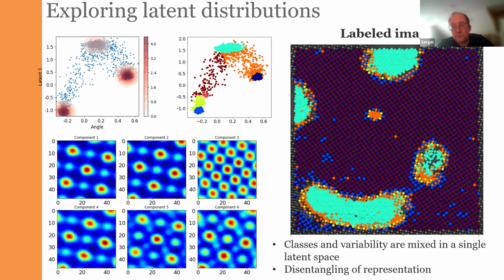We can explore the latent distributions. Similar to the cards example, the latent distribution for images like this would be dominated by the types of atoms. So we simply separate the nickel oxide layers, the A site cations and B site cations. The way we do that is we take our VAE latent distribution, and in addition to plotting the data, we also plot the kernel density estimates. That is one small thing that matters: if you have a lot of data and plot it as a distribution, we will see the outliers. But if we want to judge where the points really are, we need to add the kernel density estimate, because if we don't, our judgment of the result would be totally different.